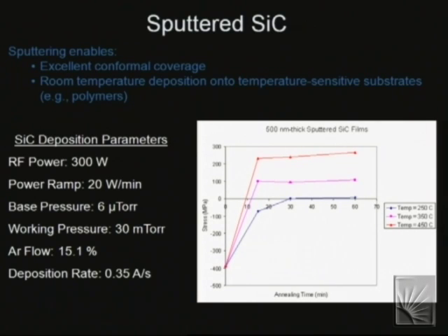So I have had enough time to digest the essence of this graph, but I can't say much more about the films other than to note the following. This is stress versus annealing time for 3 annealing temperatures, 450 C, which is our benchmark, and then of course we don't like that annealing temperature, so we explored in this experiment decreasing annealing temperatures.